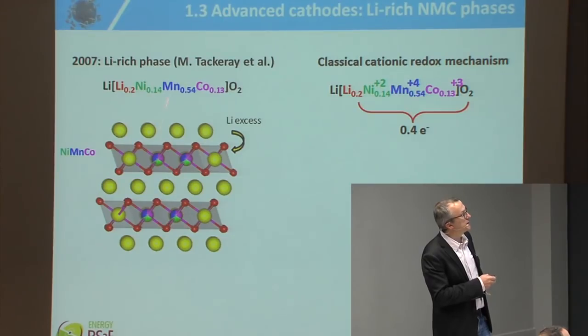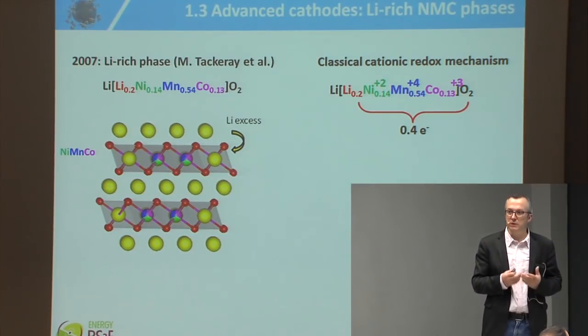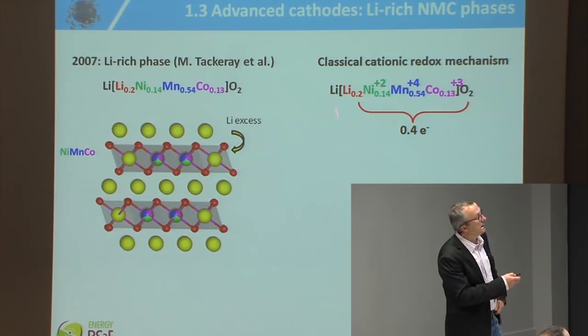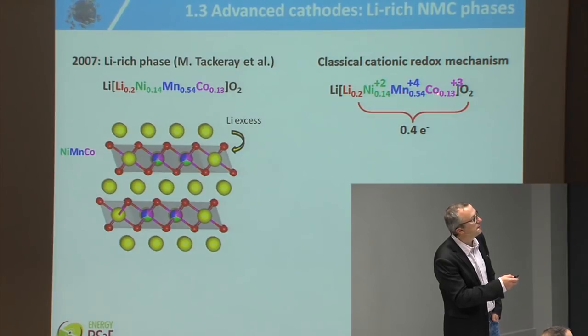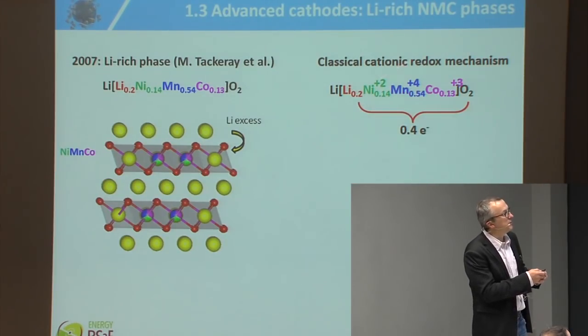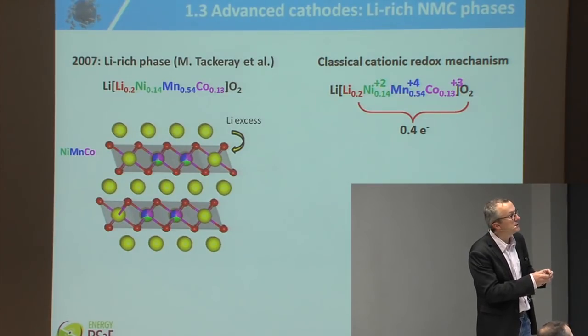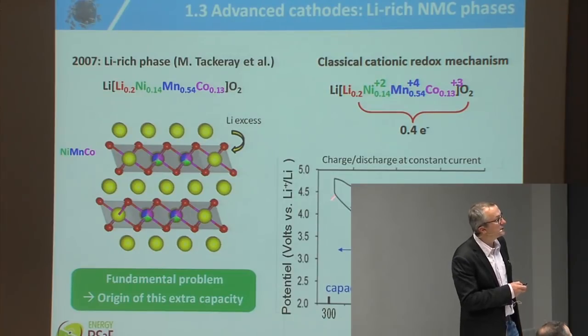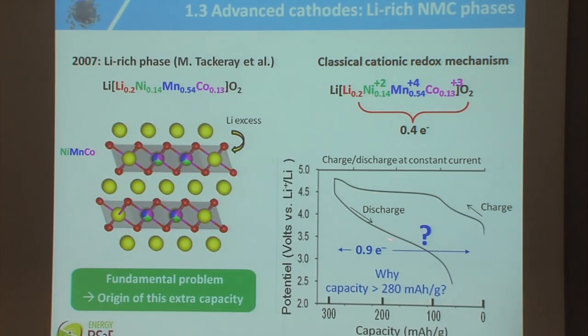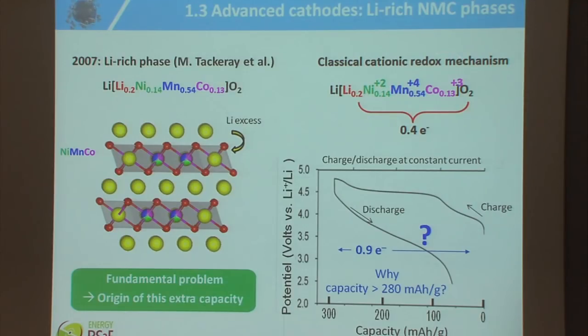But the people who did that in 2007 did not understand how it worked. If you take this structure, this is in fact nickel 2, manganese 4, cobalt 3. Nickel 2 can be oxidized up to nickel plus 4. This one is maximum. This one can be oxidized up to plus 4. So you can theoretically exchange 0.4 electrons per formula unit. And if you do cycling with this material, you can see that on discharge, this is the potential versus time at constant current, you can exchange up to 0.9 electrons. So there's a problem. Twice more capacity than the theoretical, based only on the oxidation state of metals.